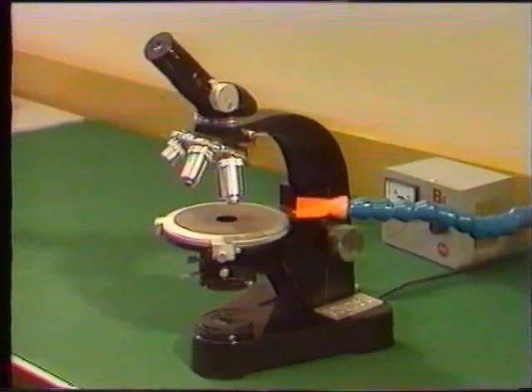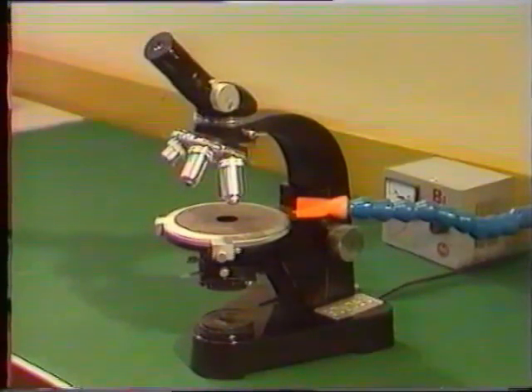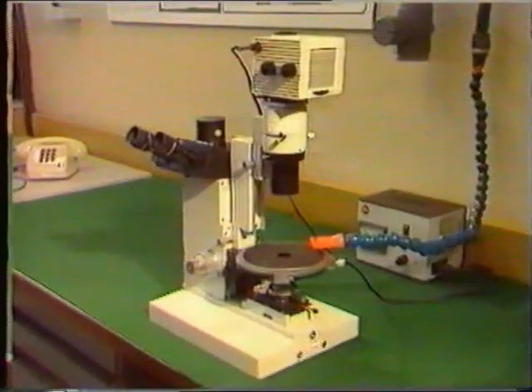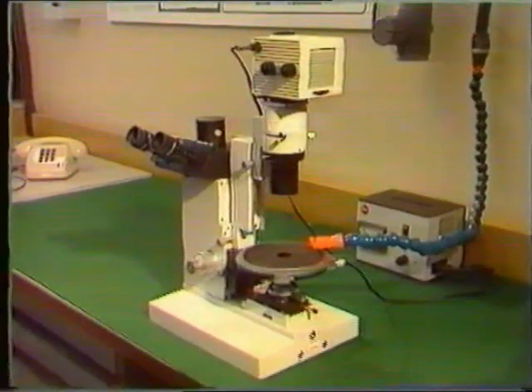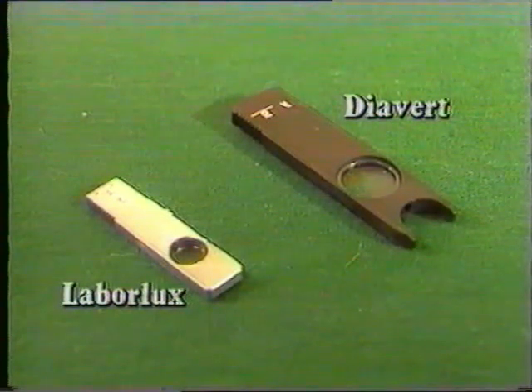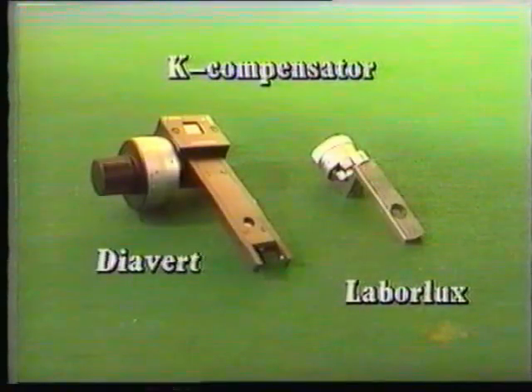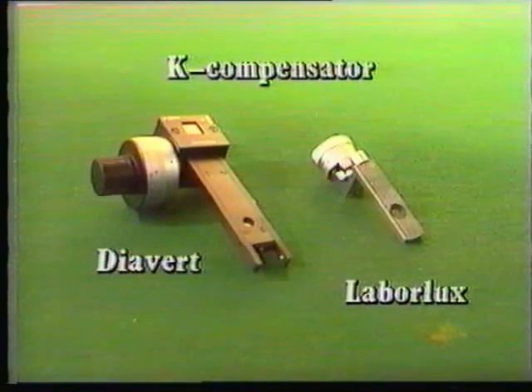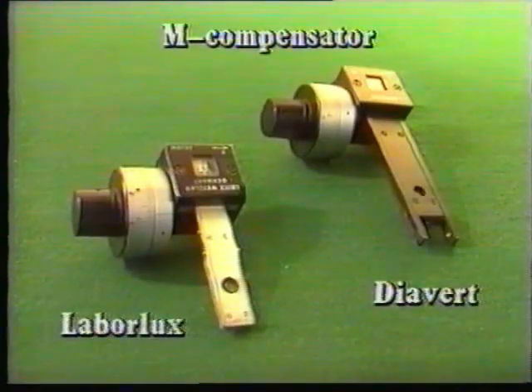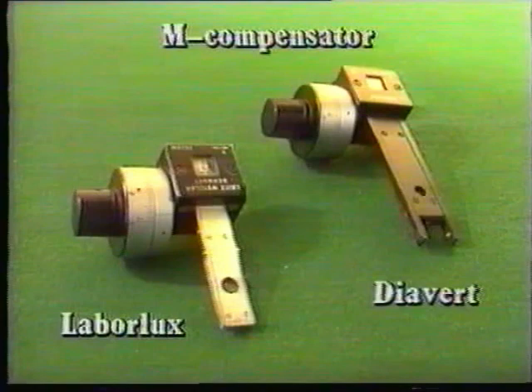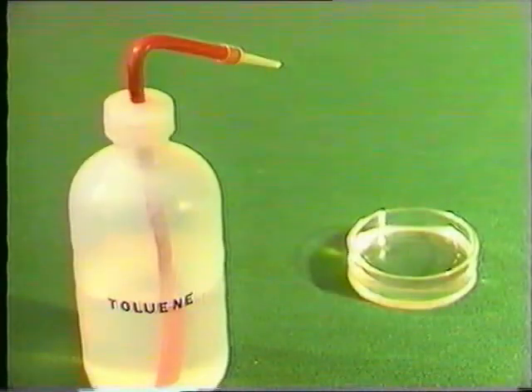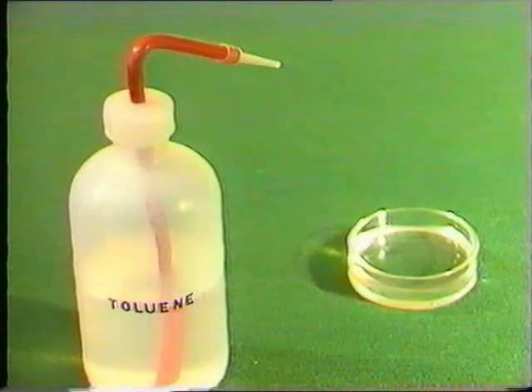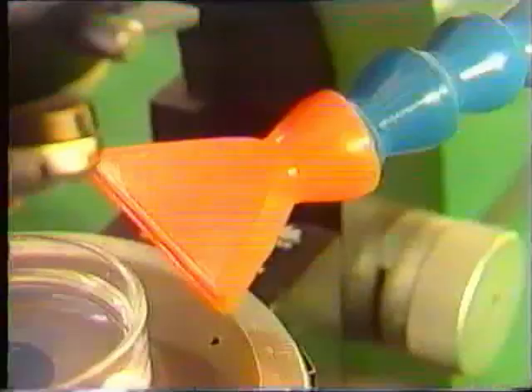Type and height of the stress in a seal of production and standard glass can be determined with a polarizing microscope, such as the Leitz Laborlux or the Leitz Diavert, equipped with a lambda plate and one or more compensators. Normally, two types of compensators are used: Type K for measuring tensile stress and Type M for measuring compressive stress. In addition, a stress-free glass cuvette containing pure toluene, pro analysis, is needed.